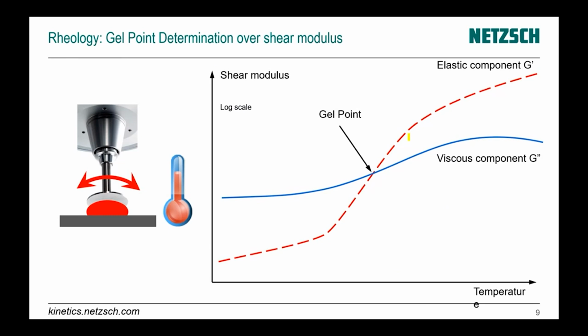Next measurement is rheology. Here we are able to find the gel point over shear modulus. The vertical axis is the shear modulus in log scale. We have two components of shear modulus, the elastic component and the viscous component. At the beginning, the uncured material is liquid and the viscous component is higher than the elastic component. Then during the curing, we have a crossing of these two components, and finally our material has an elastic component higher than the viscous component, which means the material is not liquid anymore, it is elastic or maybe vitrified. And here the crossing point is the gel point.